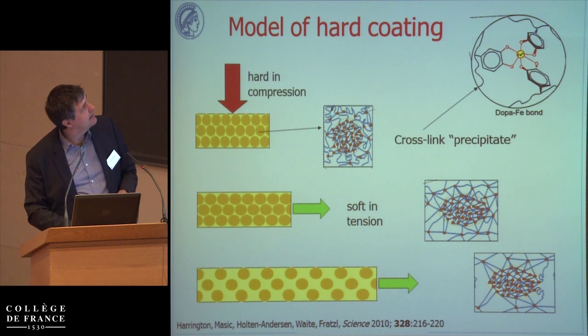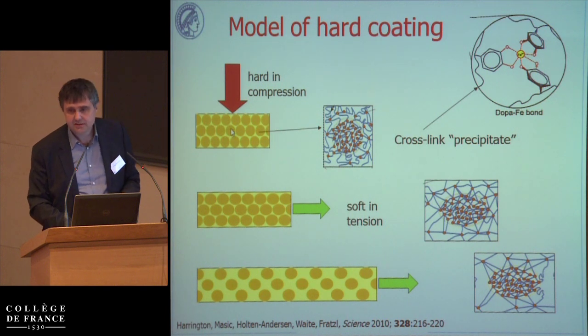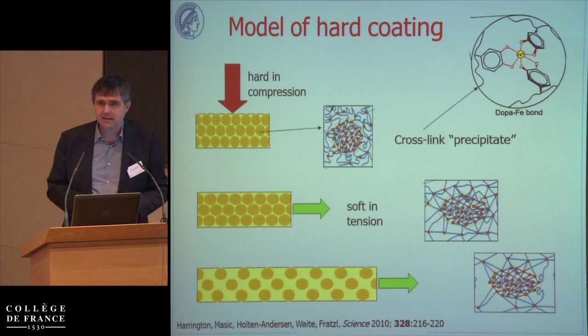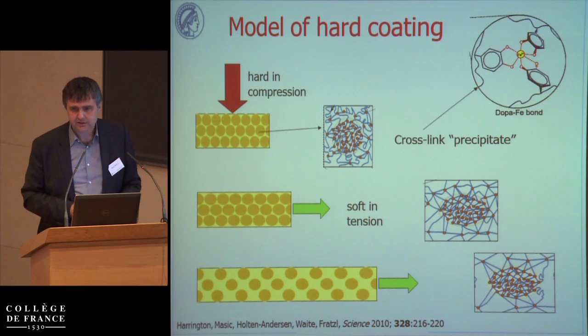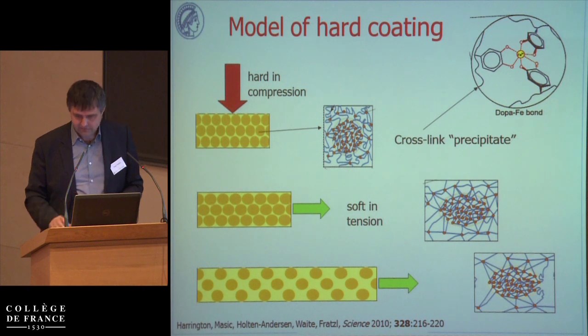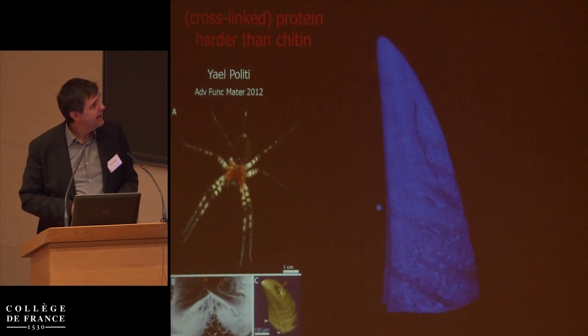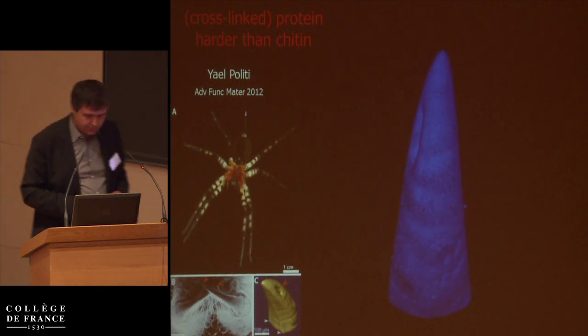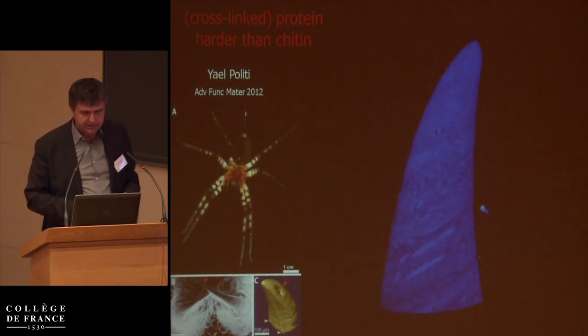Now, why is this hard in compression? Well, if I have lots of little balls here and I push on them, well, one ball hits the other ball, so this is pretty hard. However, if this goes in tension, the ball is hardly deformed. What deforms is the matrix in between the balls. And therefore, here's an extensible material that's hard in compression and therefore suitable as a wear-resistant coating for an extensible fiber. Now, this is work from Yael Politi in the lab,